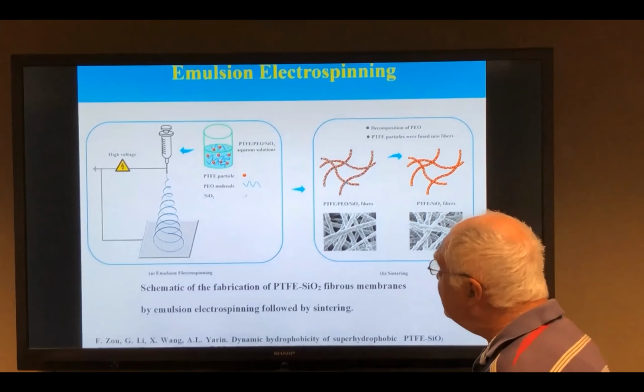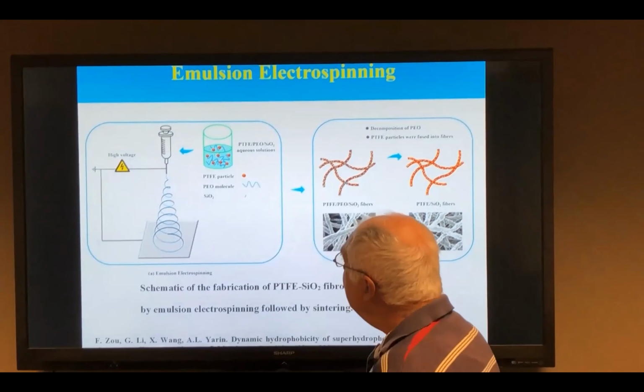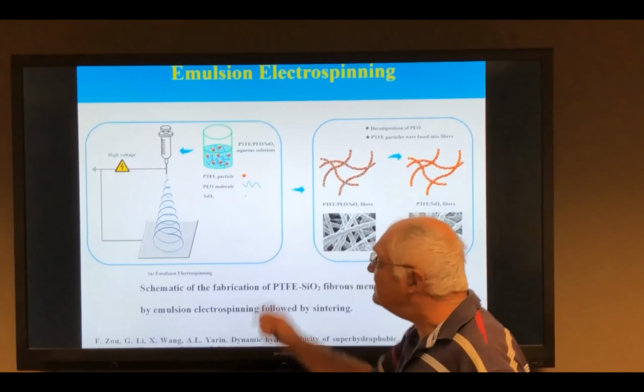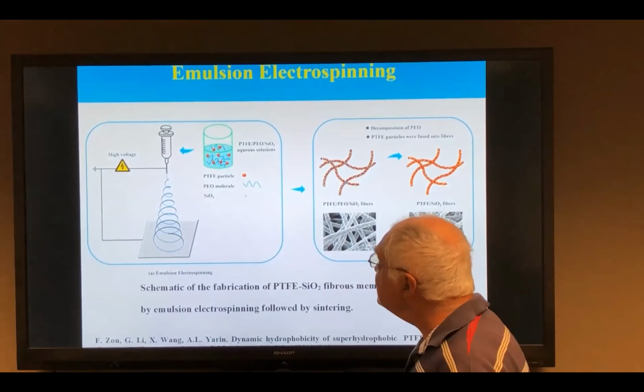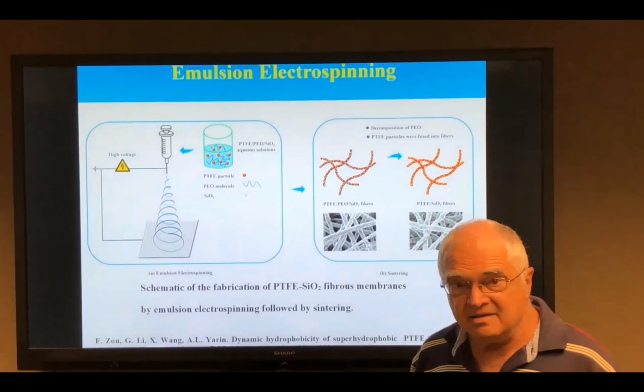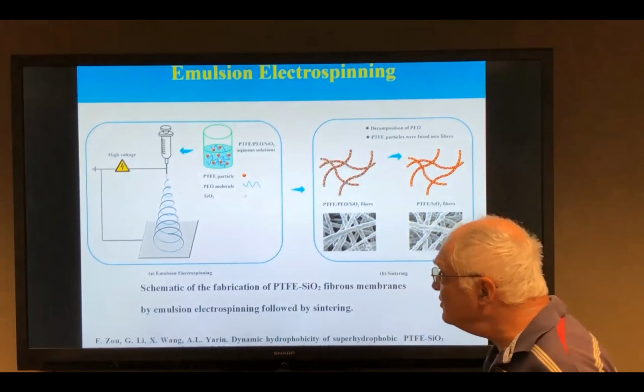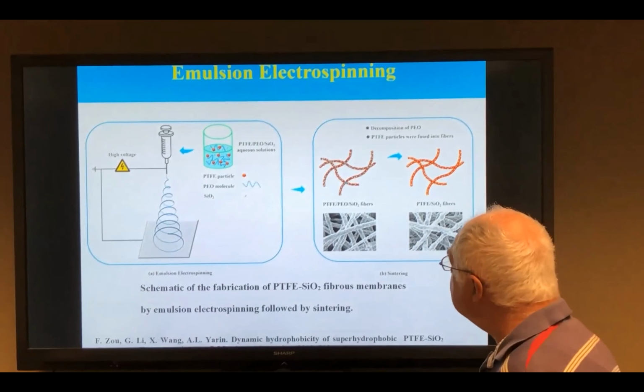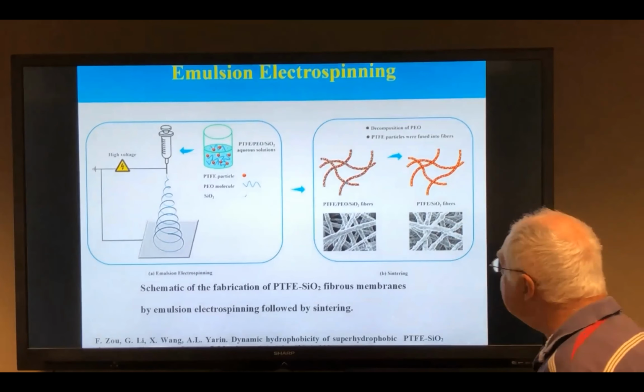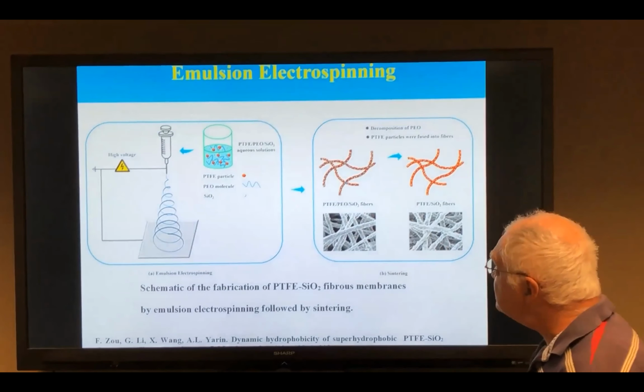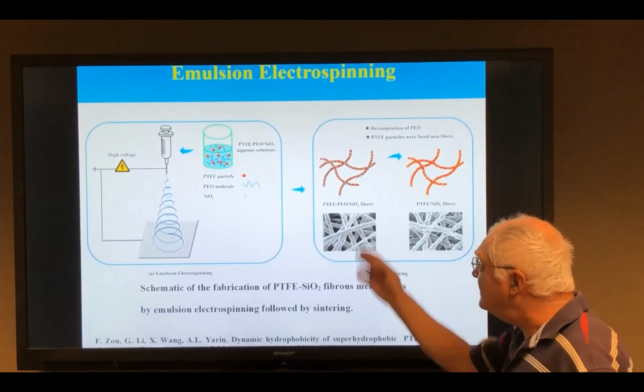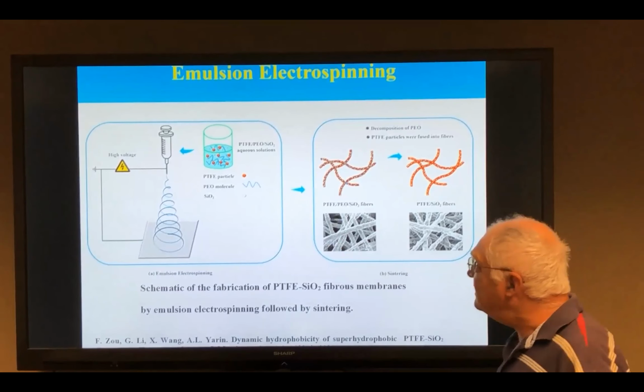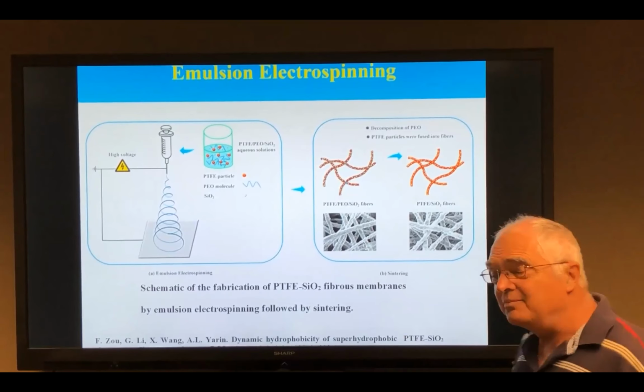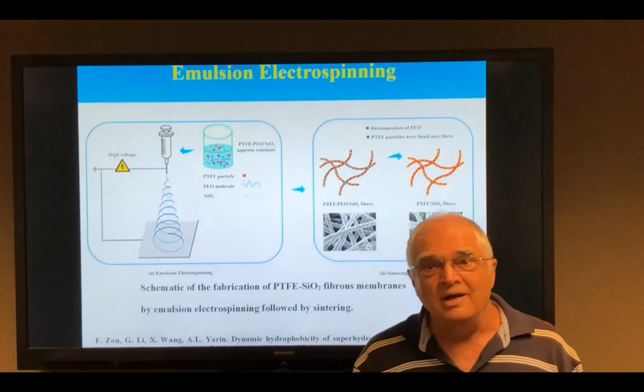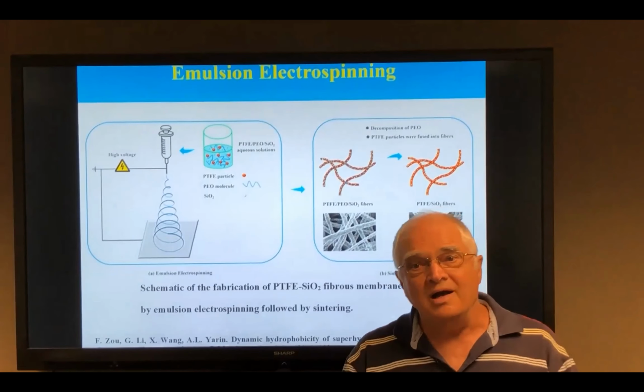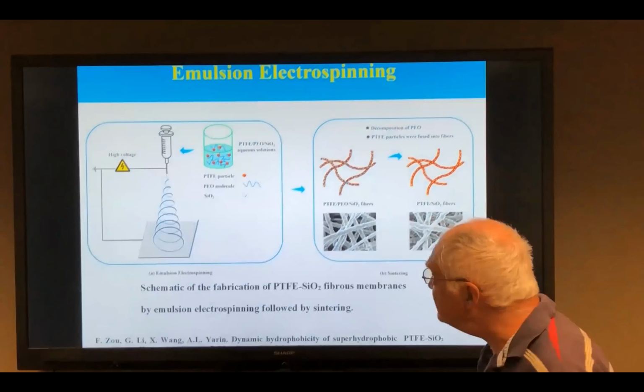This suspension incorporates a polymer solution, which is a polyethylene oxide solution, Teflon particles, and also glass nanoparticles. Each component has its own role in this process. After electrospinning, you end up with fibers which incorporate all of these materials. The skeleton of the fiber is predominantly polyethylene oxide, and there are a lot of Teflon particles and also glass particles. The point is to make this material super hydrophobic, and for that reason you need to remove the template material, which is PEO.